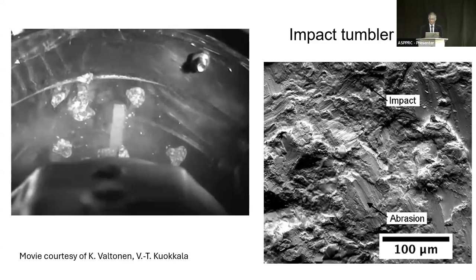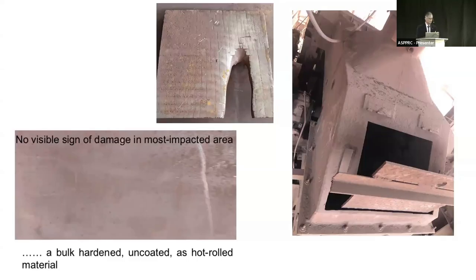From such an experiment. And I can tell you that doing experiments in a laboratory is one thing, all right? And therefore collaboration with industry is really important, because if you're trying to make a product, there's nothing like a real test of a component, okay? Because it won't be a nice granite particle inside a tumbler with rotating things. It'll be more complicated scenarios. And we installed this plate in Tata Steel, where there were minerals falling. And the conventional plate that they use is illustrated here, which is mild steel with hard facing coating. And you lose that in about 3 months, okay?